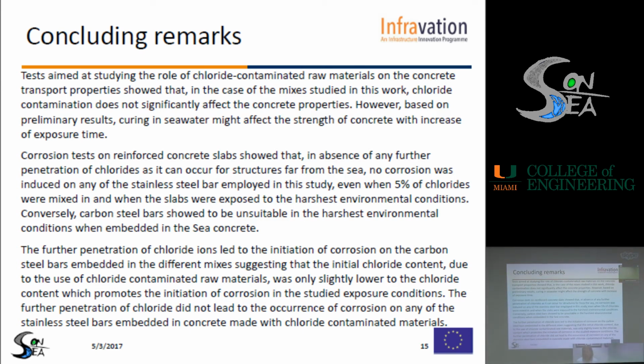The further penetration of chloride ions led to the initiation of corrosion on the carbon steel bar embedded in the different mixes, suggesting that the initial chloride content, due to the use of chloride-contaminated raw materials, was only slightly lower than the chloride content which promotes the initiation of corrosion, that is, the critical chloride threshold in the studied exposure conditions. The further penetration of chloride did not lead to the occurrence of corrosion on any of the stainless steel bars embedded in concrete made with chloride-contaminated material.